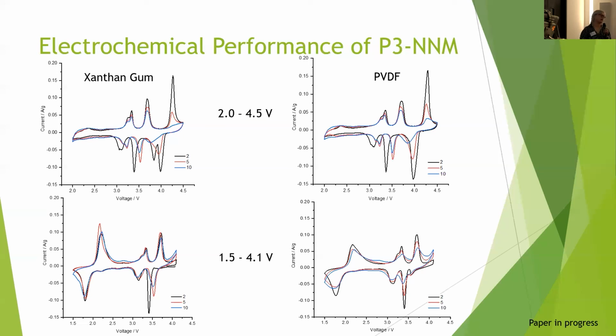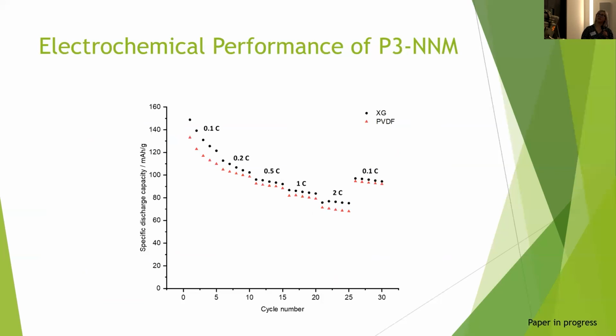But there are also other things that happen in the material in these voltage ranges that I need to figure out. But all in all, there's not much difference between the two when using the different binders. So you see that xanthan gum is, again, stable in these different voltage ranges. And then again, I looked at different cycling rates, and when I use both of the binders, they both perform perfectly fine and similar to each other.